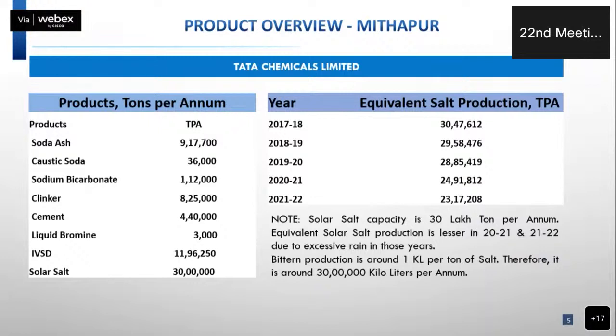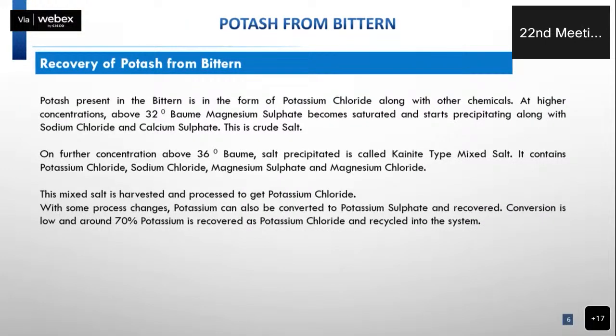Solar salt production for the last 5 years is given here. It is ranging from 23 lakhs to 30 lakhs tons. Actually, bittern generation is around 1 kiloliter per ton of solar salt. So our bittern generation is also around 30 lakh kiloliter per annum. Bittern coming out after the salt harvesting is at around 29 Baumé, and it contains potash concentration of about 21 grams per liter. This is in the form of potassium chloride.